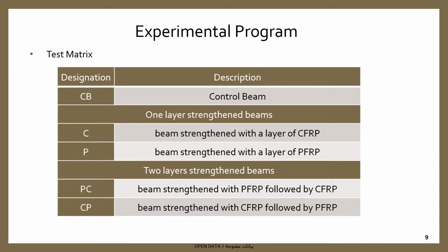The beams have some variations such as the type of FRP, since CFRP and PET-FRP were used, the number of FRP layers, and the stacking sequence. The first beam was tested as a control specimen. Two beams were strengthened with one layer of CFRP and PET-FRP. Finally, the last two beams were strengthened with two layers of both strengthening materials with different sequences.